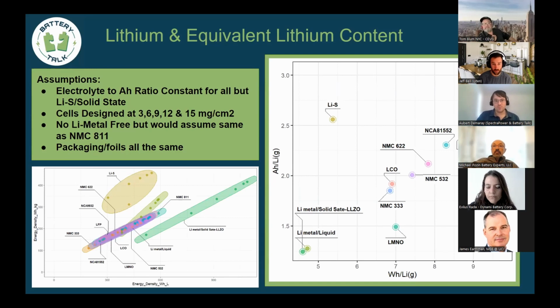And then we kept all the cathode loading. We basically swept a bunch of cathode loadings, 3, 6, 9, 12, and 15 milligrams per centimeter squared for each of these chemistries. And then we said we wouldn't do lithium metal free anodes. One, they don't really work, but two, it would basically be NMC 811, because you'd be replacing the graphite with just a bare sheet of copper. So you would have roughly the same amount of lithium in the system anyways, because your amp hours to electrolyte would stay constant. And then packaging and foils are all the same.